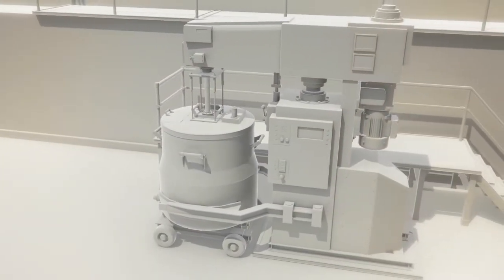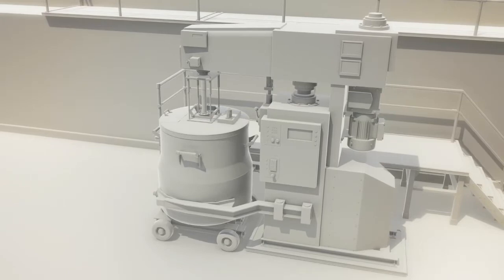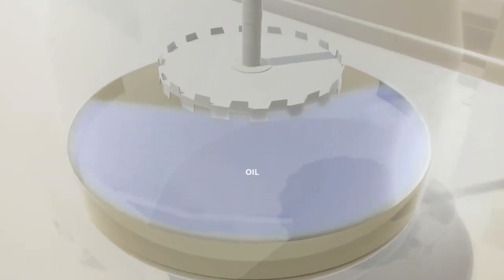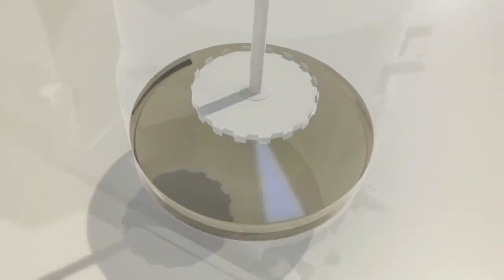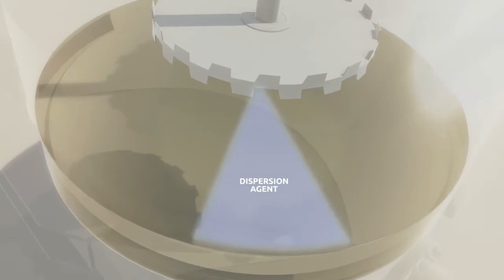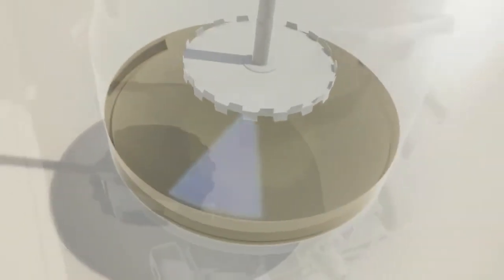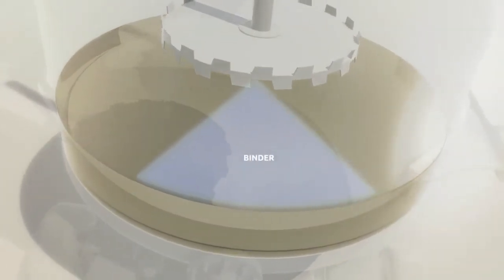To create the liquid master batch, first several components are mixed together to create the oil-based liquid carrier. For example, a processing agent that speeds up its melting process, a dispersion agent to assist the dispersion in the target polymer, and a binder to hold everything together.